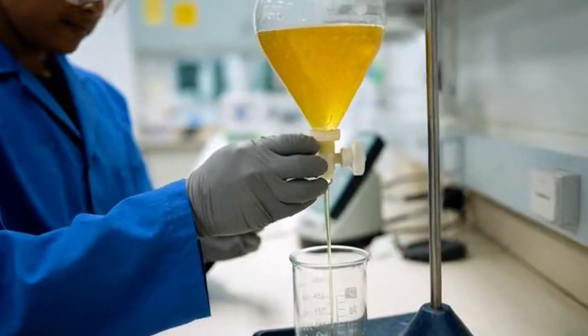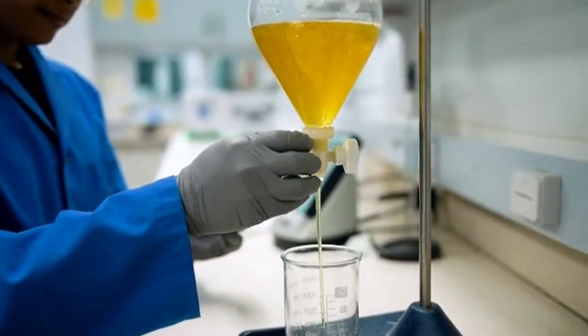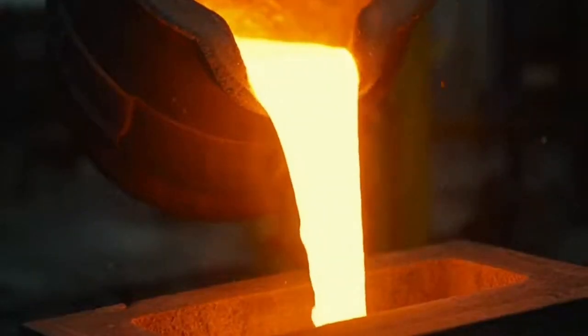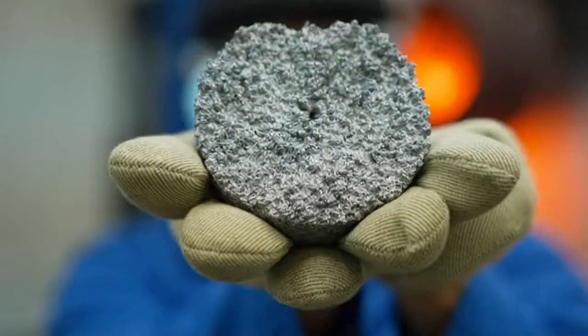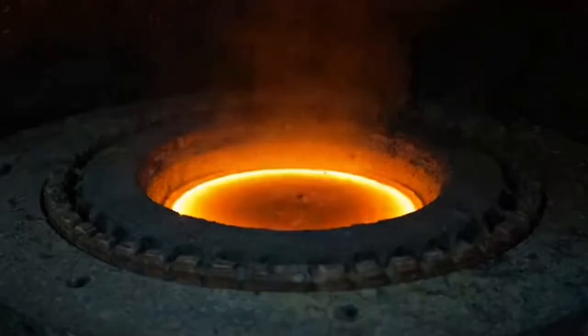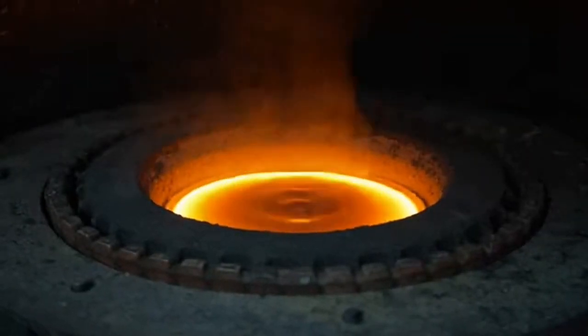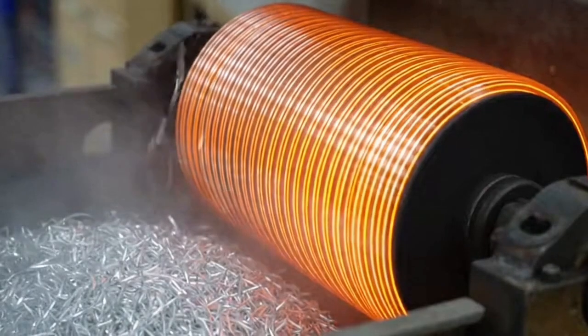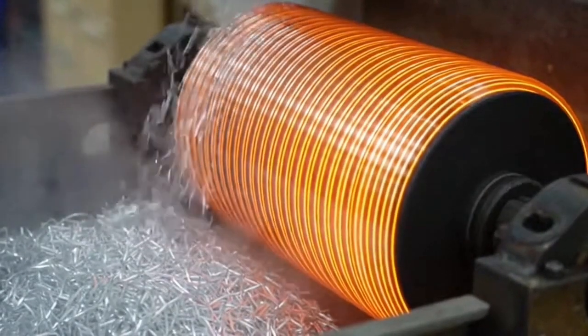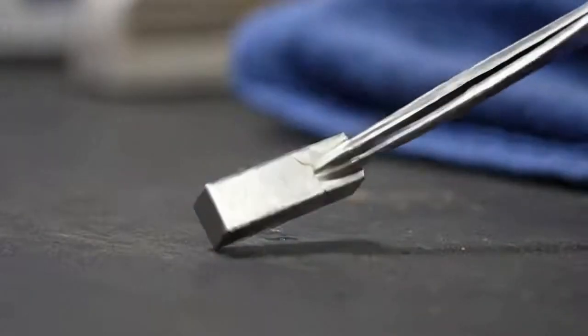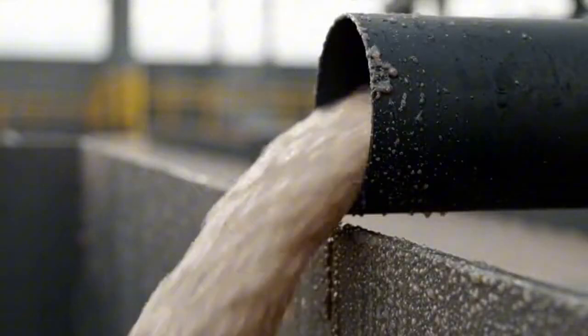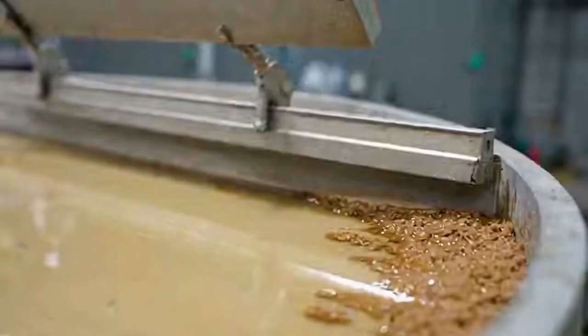You melt the charge under vacuum or inert gas. You strip cast the melt into thin, rapidly solidified ribbons so that the right hard magnetic phase forms with grains that will later accept orientation. Those ribbons go through hydrogen decrepitation. Hydrogen sneaks into the lattice and blows the ribbons apart along grain boundaries in a way that is almost gentle.